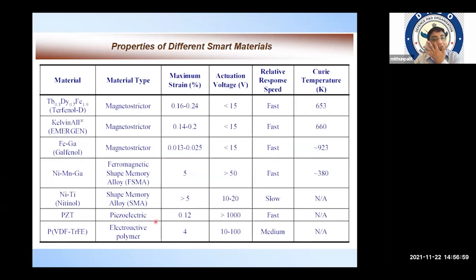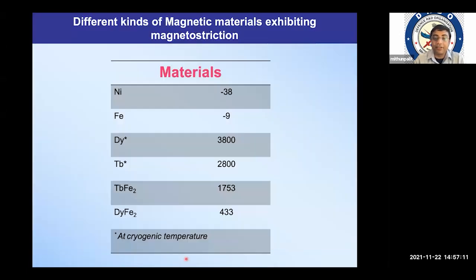And PZTs are very good, but PZTs also show 0.1% strain. However, the voltage requirement as an actuator is very high, and electroactive polymers also require quite a bit of high voltage. Regarding the magnetostrictive material, there are different materials. However, you can see that pure rare earths, dysprosium and terbium, show very high values. These values are reported in ppm, that is parts per million.